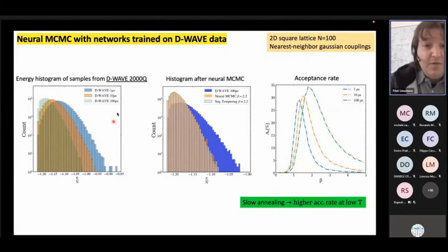As we expect, for the longer annealing time, that here is 100 microseconds, the energy distribution has more weight on low energy configurations, and here actually we sample frequently also the ground state. Okay. What is interesting to see is that when you train your neural network on such data and you perform a Monte Carlo simulation, you get an exact Boltzmann distribution.